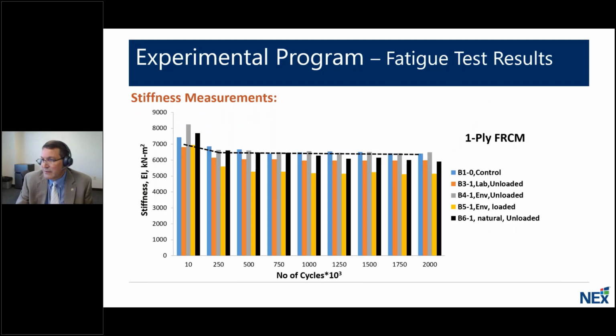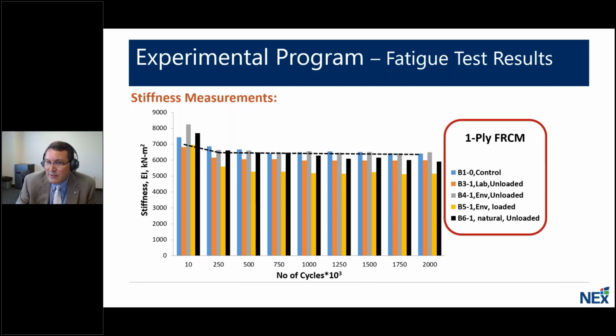If we look at that in a histogram plot, here you can see this in terms of 250,000 cycle increments. And here we're looking at the one-ply system of FRCM. It may be noted in general that there is a minimal drop in the stiffness as cracks continue to propagate and develop, and then the stiffness stabilizes. You can see color-coded the control specimens, lab specimens without stress, environmental condition specimens without stress, with stress, as well as the external specimen in the outdoor environment that is unloaded.